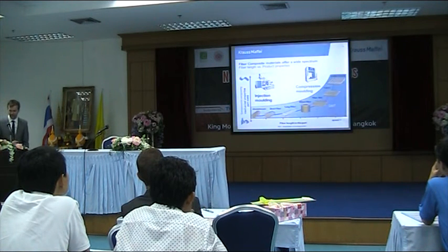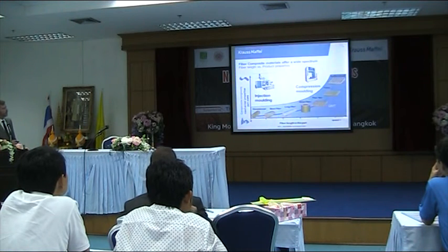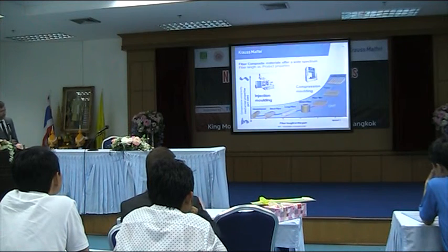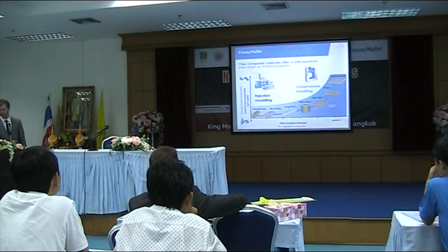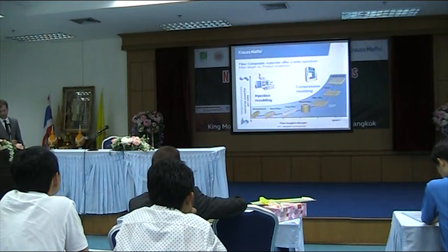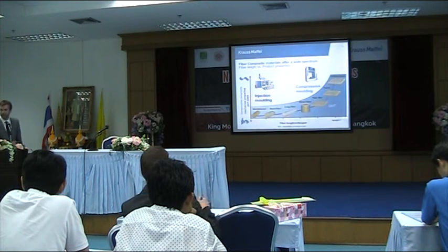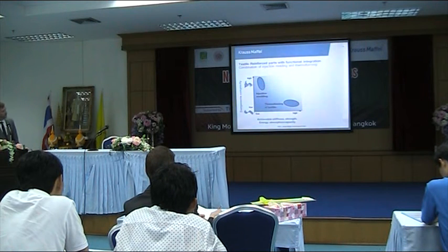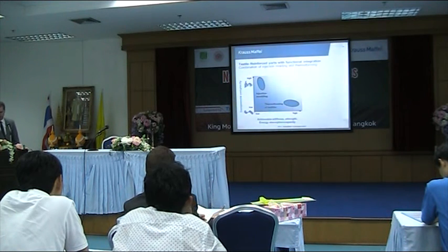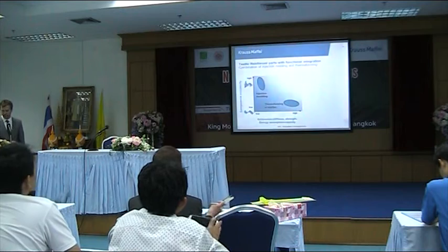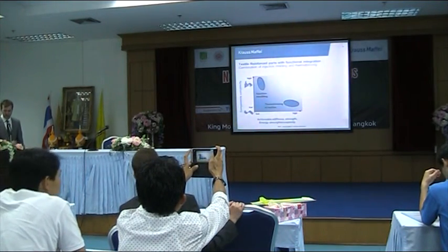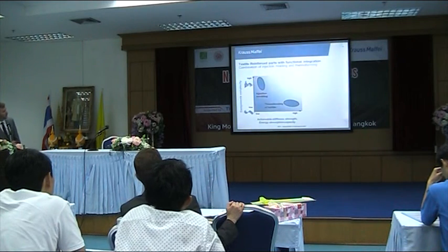And with injection molding, you have high choices of complexity of your parts. And with compression molding, you have the advantage in fiber lengths and material properties. So you can see what makes sense: you combine both technologies. So this is what Krauss Maffei did. On the one hand, injection molding technology, and on the other hand, thermoforming technology. So you can achieve very high stiffness, strength, and also energy absorption capacity. And you can achieve high component complexity.